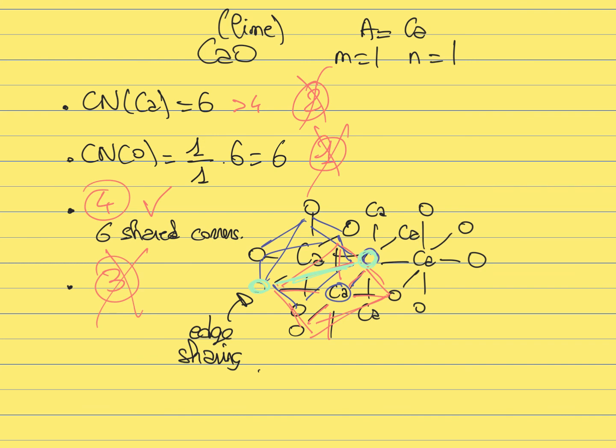And if an oxide substance can satisfy simultaneously those 4 rules, then you know that the connectivity is high enough, but not too high. In that case, there is a good chance that this oxide will indeed be able to form a glass. If you melt a liquid and then quench it, it's going to be more likely to vitrify into a glass rather than crystallizing into a periodic crystalline structure.